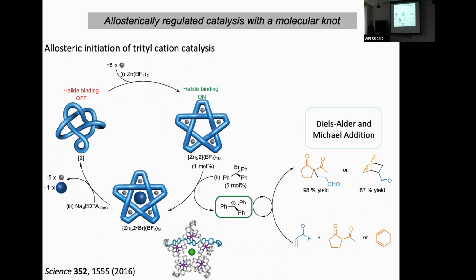So when you've pulled the metal ions out, this knot won't bind to chloride or anything else because it's missing the metal ions. But we can reintroduce metals, and the easiest one to introduce is zinc, because it has the same sort of coordination geometry as iron, but it has much faster kinetics. So by adding the zinc, it reassembles this anion binding site. And if we've used BF4 ions, they don't go inside. So this has got this empty cavity that's a very strong binder of halides.